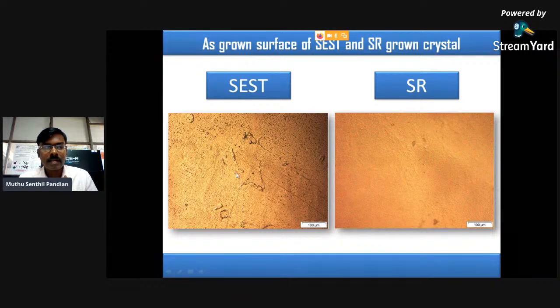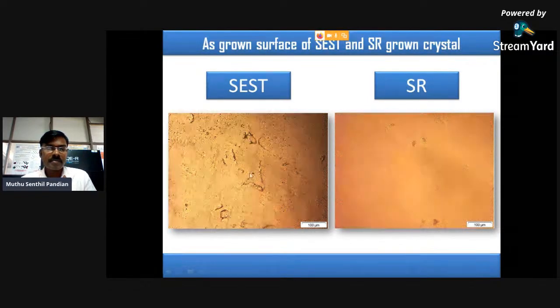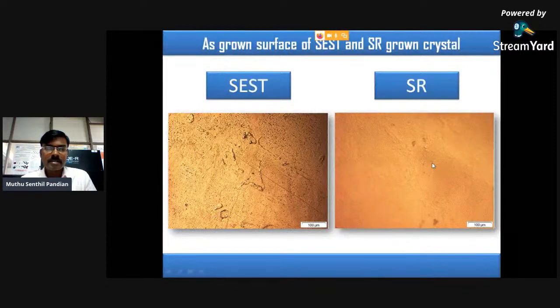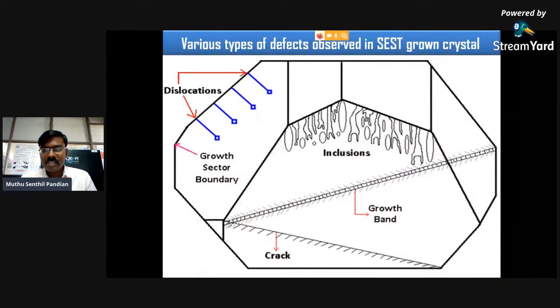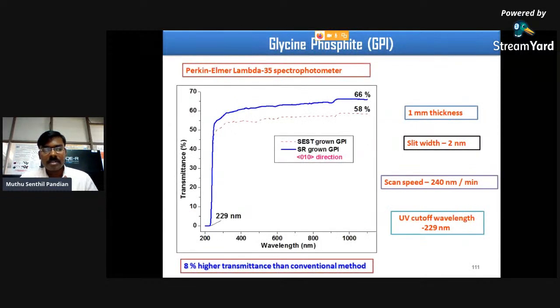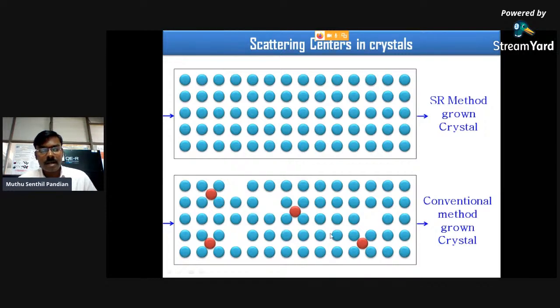A lot of roughness appeared in the conventional method grown crystals. In the case of the SR method, there is also some roughness, but compared to the conventional method, the roughness of the SR grown crystal is less because of the higher crystalline perfection. There are a lot of dislocations appearing in the conventional method grown crystal. Scattering centers play the main role in reducing the optical properties of the grown crystal. In the conventional grown crystal, a lot of scattering centers appeared, but in the case of the SR method there is higher crystalline perfection, so fewer scattering centers appear in the SR grown crystal.